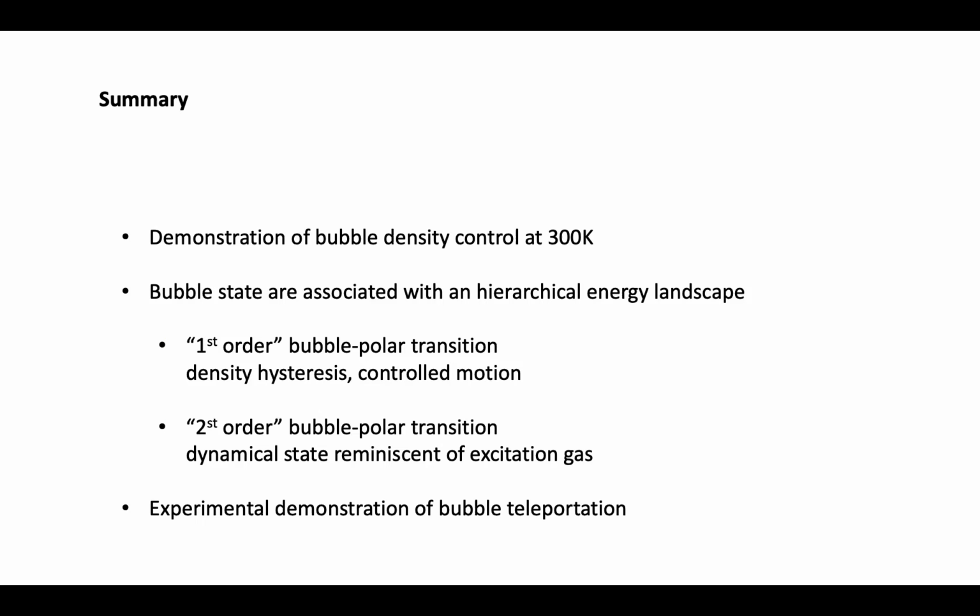What was found is that, depending on the character of the phase transition between the bubble and homogeneously polarized states, one can have either a hysteretic behavior, which allows you to have many different metastable bubble configurations, or, in case of the continuous transition, we obtain this dynamical state, the excitation of bubbles, which is very much similar to those domain polar liquids that were discussed previously during this conference.